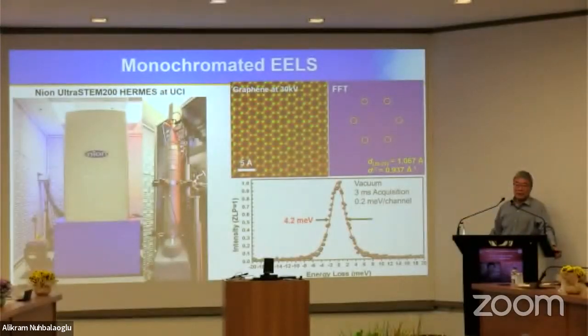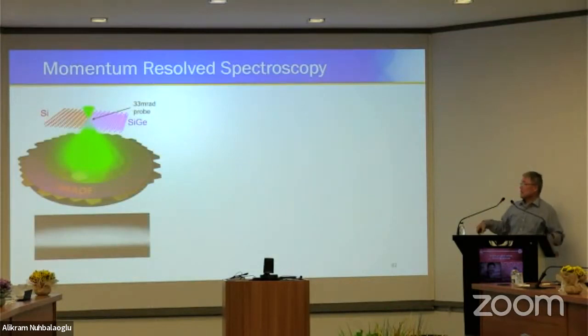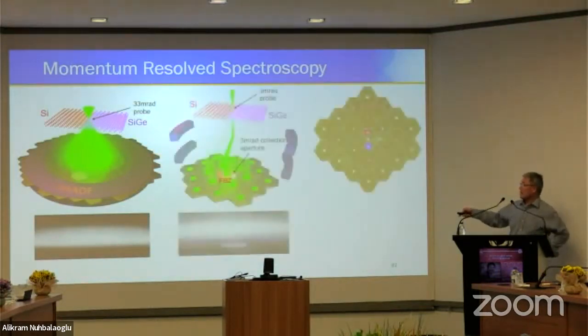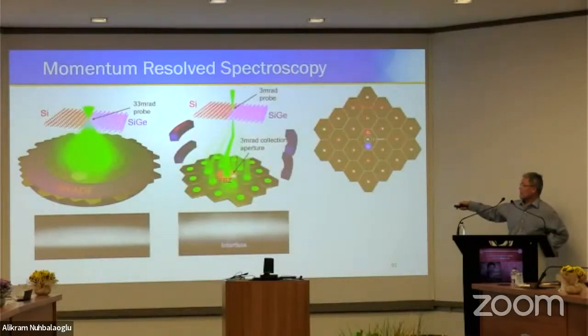But there is a more dedicated setup where you can study very small energy change. So this is one of the instruments in our lab, which is quite unique. At 30 kV operating voltage, we can get a 4 milli-electron volt energy resolution. This is a very important development. So with the EELS method, we can study the diffraction of electrons in the scanning TEM. With a large converging angle, all the diffraction disks are overlapped. There's no distinguishing between different angles. However, if you reduce the converging angle, you see many different spots. Each of these diffraction spots will tell you the scattering to a particular angle. And then if you can analyze electrons scattered to different angles, you will see the angle-resolved scattering of the electron beam by lattice vibration.